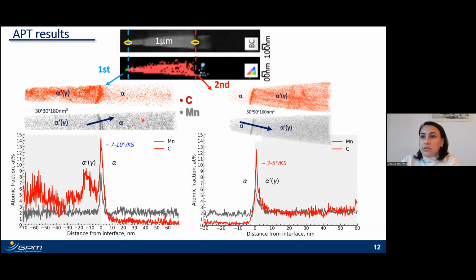As you can see on this slide, the 3D reconstruction of carbon and manganese atoms for both volumes with both interfaces. And we could plot the compositional profile perpendicular to the interface. Here it's important to say that even if you have a profile for both carbon and manganese, in this study we will mainly focus on the interpretation of manganese segregation, since the origin of carbon segregation in our case is questionable due to its high diffusivity even at room temperature. But the carbon composition changes from the carbon-rich martensite to the pure carbon-free ferrite zone.